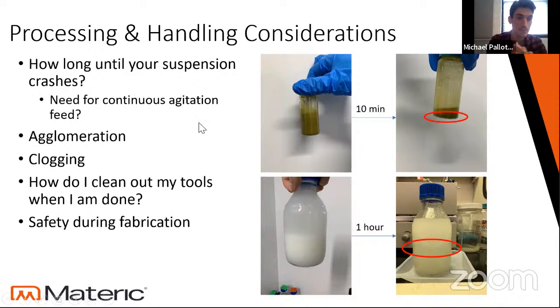In terms of what actually happens when you're spinning, we'll talk about environmental conditions in a bit, but making sure that you have your solution uniformly dispersed in terms of the nanoparticles to avoid agglomeration becomes huge, because you'll end up clogging your system, whether it is a needleless or a needled system. And once your nanofiber production method clogs, you effectively will lose that solution. When you're dealing with additives that could be very costly, that's a huge detriment, with slowdown and money lost at that point.